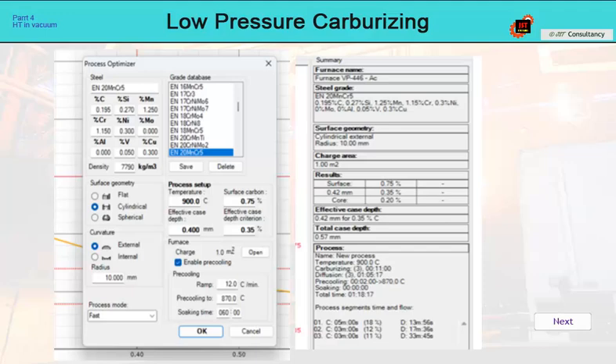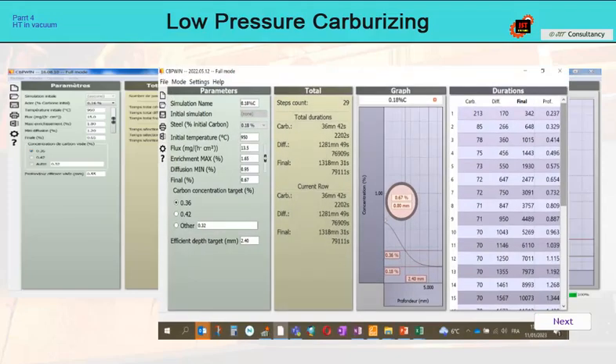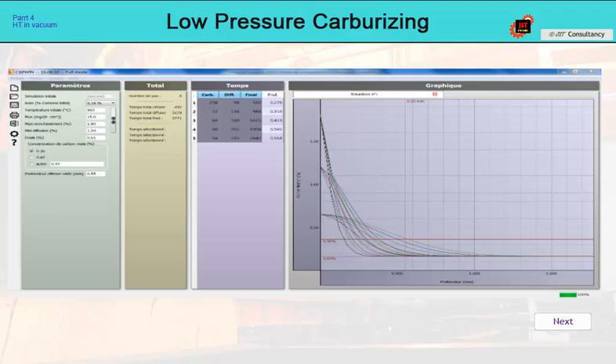Infracarb and ECM differ significantly from these simulation systems with calculation of carbon flow based on surface area. Whether we have a small or large surface inside the furnace, the amount of acetylene is always the same and corresponds to the maximum possible batch surface area in the device, for example of 25 square meters. We therefore do not need to know the batch surface. This has its advantages. On the one hand, there is always a sufficient amount of gas in the furnace, and it cannot happen that some parts of the charge are not carburized. On the other hand, we only have one program for all batches of the same material, for the same CHD and at the same temperature, regardless of the surface area of the parts in the batch. The question is, why is this so?